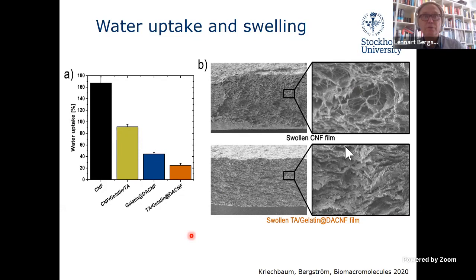First of all, let's look at the water uptake and swelling. So regular CNF film, or the ones we are using, have a very large water uptake - 160% of its own weight. If we just mix CNF, gelatin, and tannic acid, we reduce the water uptake to 90%, but this is not a major increase.